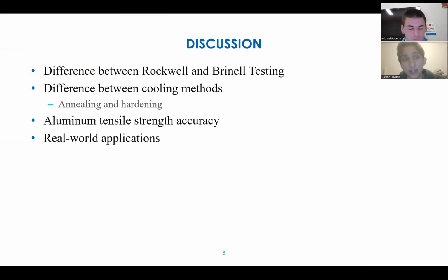And then this really highlights the difference between the Rockwell and Brinell testing, as I mentioned beforehand. There is a clear difference between the cooling methods based on the bar charts, because the water quenching was fluctuating a little bit between B and C, but the oil actually was very steady in terms of not the accuracy, but the strength that it gave the material. So that was very interesting. Then the aluminum tensile strength accuracy again was very important in determining the accuracy of the Brinell test. And then of course this has a lot of real world applications because we need things to be very accurate in their own strength, whether that be to build bridges or buildings or anything that has a load bearing on it and is reacting with different shear forces or tensile forces.